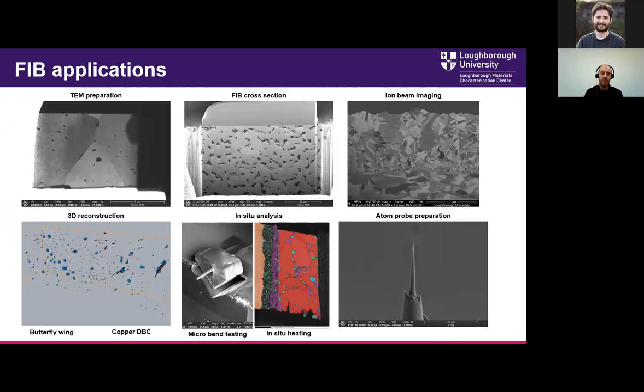TEM sample preparation is probably one of the key uses that FIB has. And I like to think of this as suddenly we have a polishing lab inside the chamber. FIB cross sections are another really useful application of FIB, where we want to mill dissimilar materials of different hardnesses. This is especially useful for very soft materials like tin, where they're very hard to polish manually, but with an ion beam, suddenly they're quite easy to polish. Ion beam imaging generally gives you very good channeling contrast. So if you want to identify grain boundaries, but you don't want to do EBSD, it's not required, then this is a good way to go.